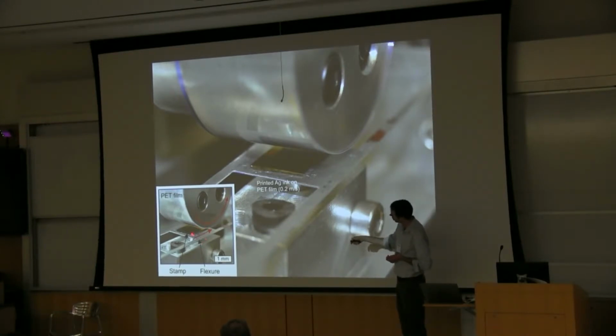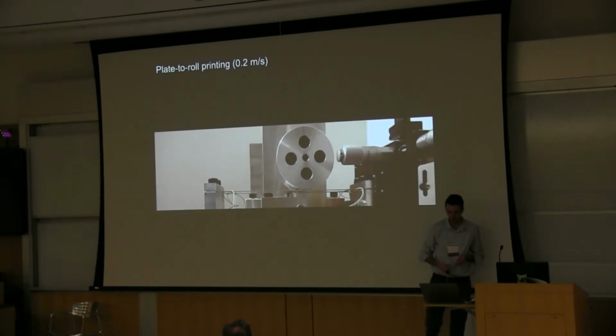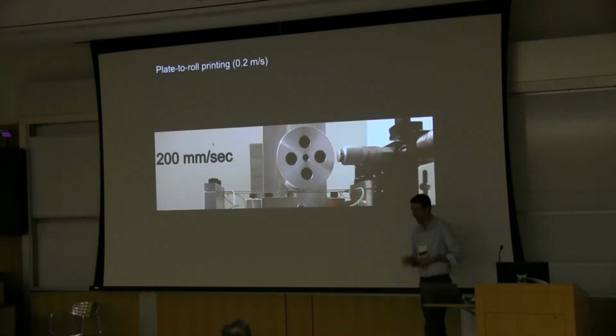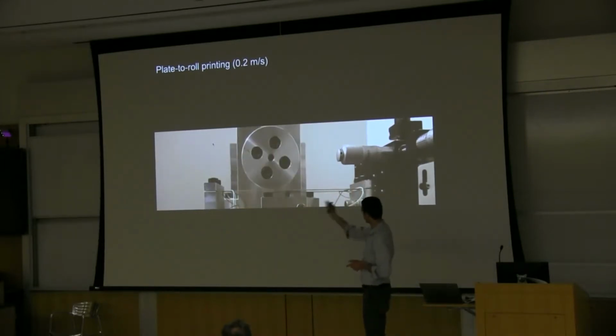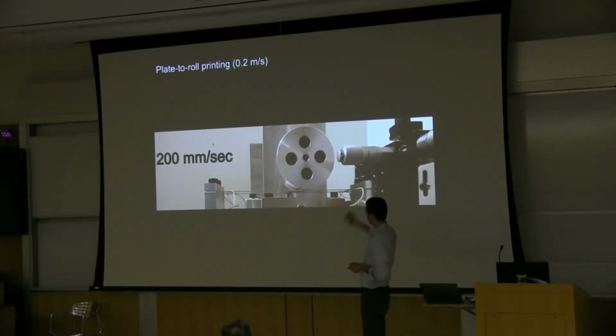And this is a flexure, a simple compliant mechanism with a capacitance sensor underneath it, which lets us control and measure the printing force. And using this, we can do printing so far up to the limit of the actuation system. And you'll just see the roller zap back and forth in real time. And this is about 0.2 of a meter per second.